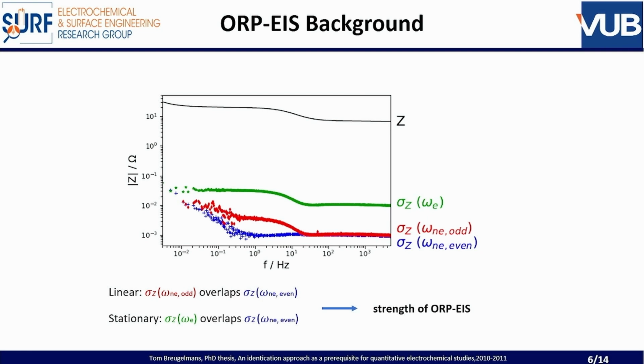One of the things that we can do is to play with the amplitude and see at what level you introduce non-linearities, and lower the amplitude to avoid non-linearities. It's something that is neglected at the moment, but in the old times, when I started to do impedance measurements, you were using an oscilloscope, and you were looking at the semicircle or the ellipse to evaluate whether you had linearity. Now it is not considered anymore in impedance measurements, but it is important.